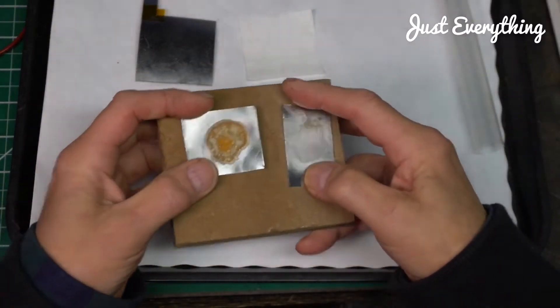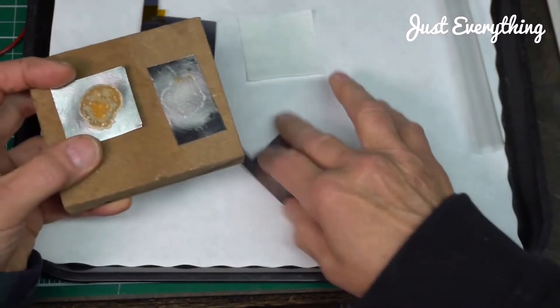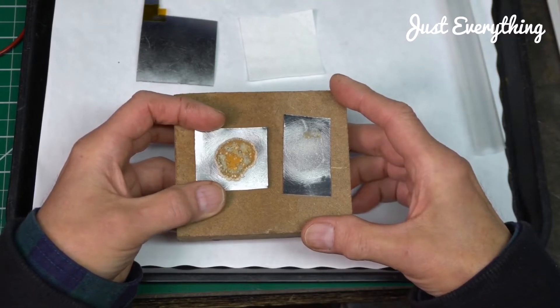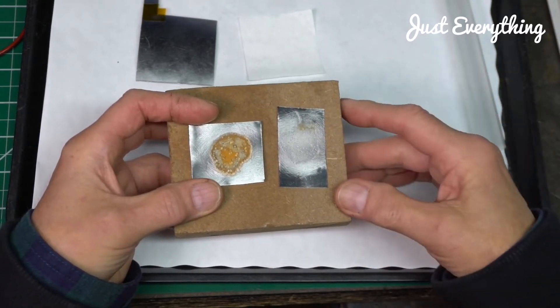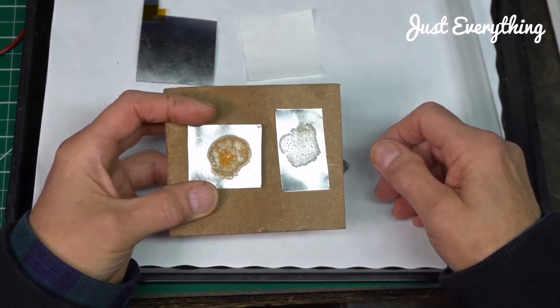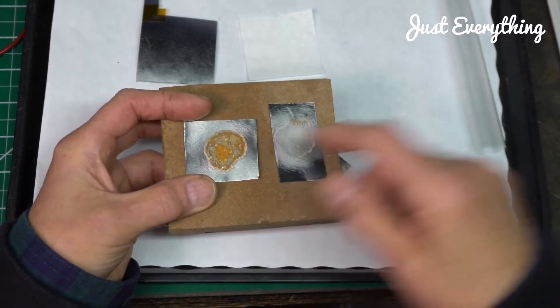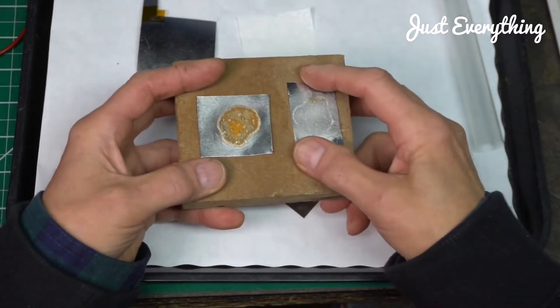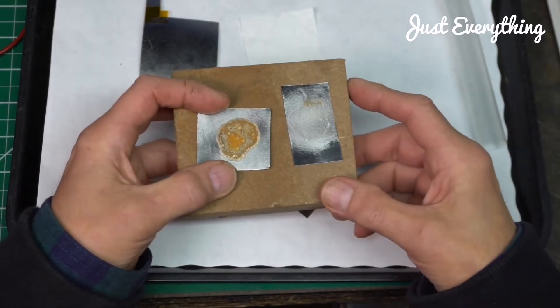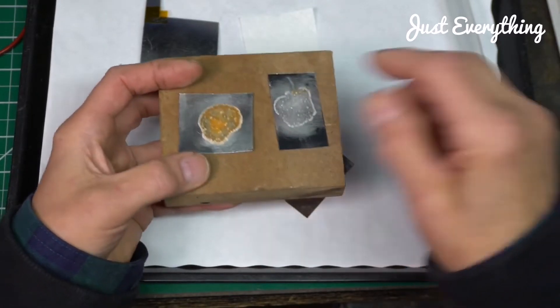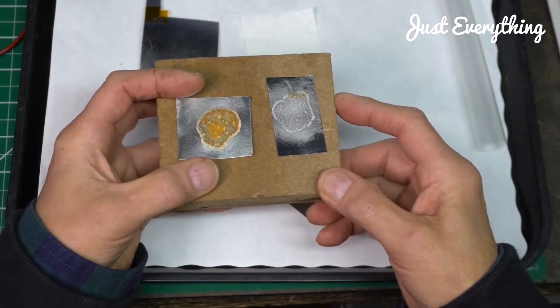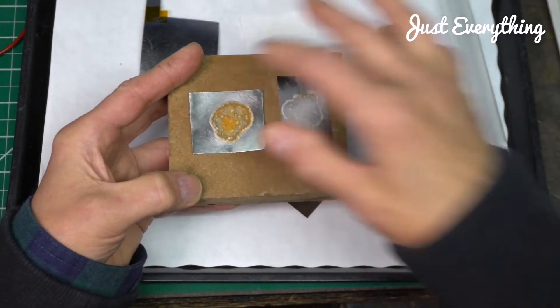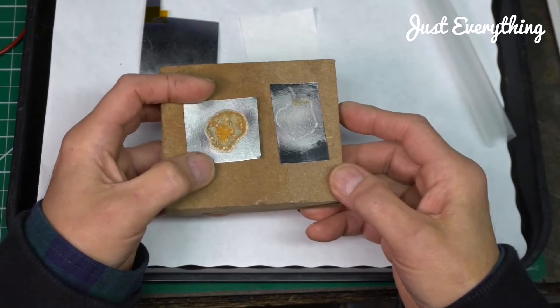That's all you have to do is you get your material that you want to test, your iron that you want to test. Make sure all oil is removed from it. And you can use acetone or alcohol or just scrub it with soapy hot, warm soapy water to get off the grease. And then you scour it up with sandpaper or emery cloth. And then next you just take some salt solution, ordinary table salt and water solution and put a few drops on the sheet you want to test and just leave it overnight.